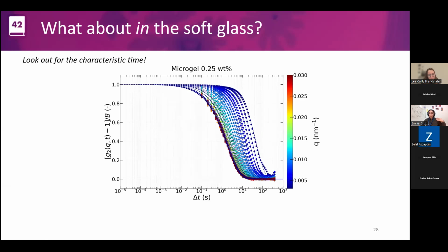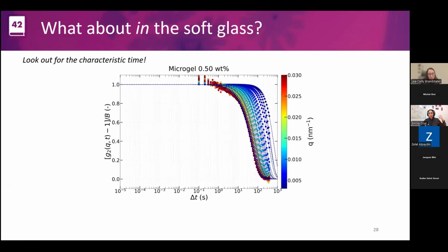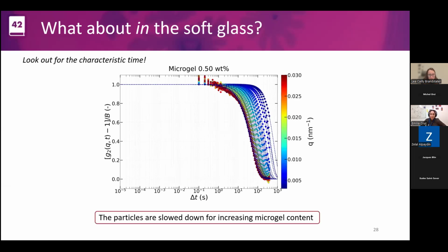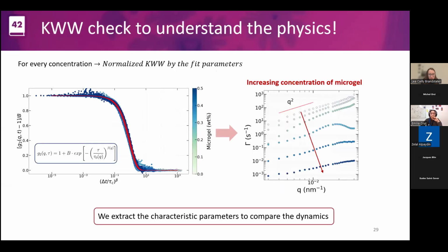We see that the particles will always be in Brownian motion within the pocket, no matter the microgel concentration, actually. So we look out for that characteristic time and we notice that the particles have been slowed down with increasing microgel content. Now, because we have a really cool model that can model this exponential decay, we extract the characteristic parameters to try to compare the dynamics of these different regimes, so below the glass transition and above.